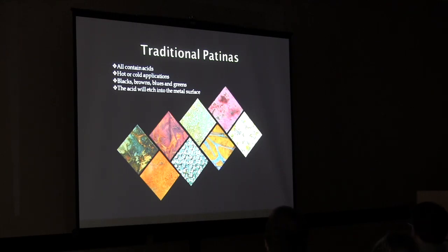Okay, and this was 3 patinas combined. The base patina here was liver sulfur, which is a cold patina that turns from a gold to a black, depending on how you put it on. Okay, and then the second patina is ferric nitrate, and that's these kind of yellowy colors. And then the third one here is titanium oxide mixed with ferric nitrate. Okay, titanium oxide is really nice. It's what all paints are made of, basically.